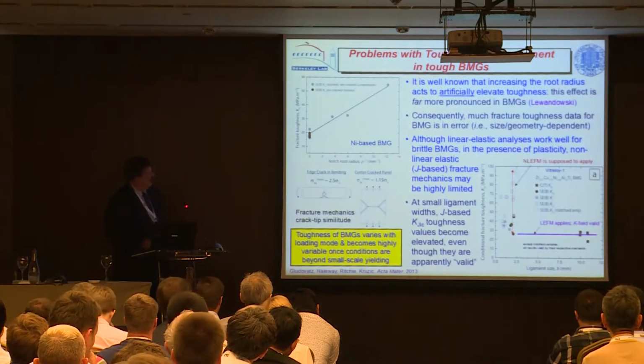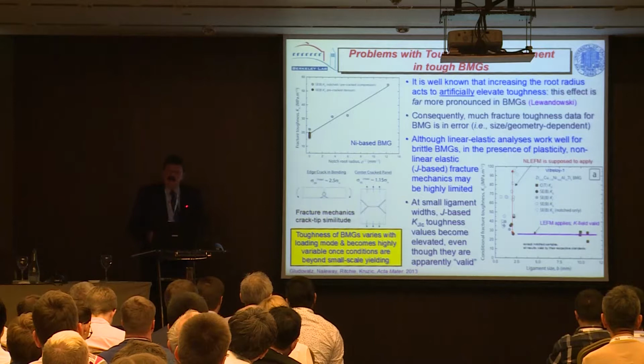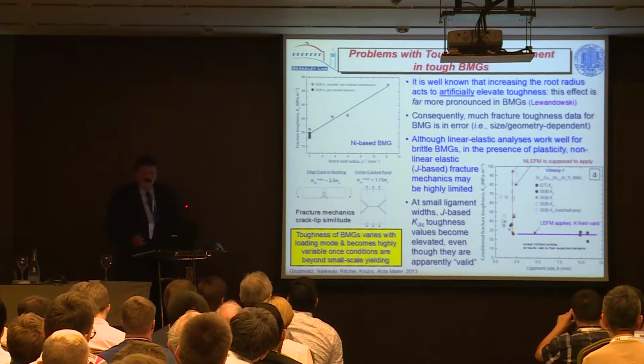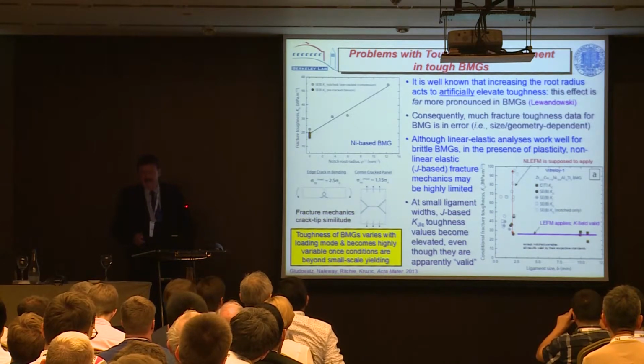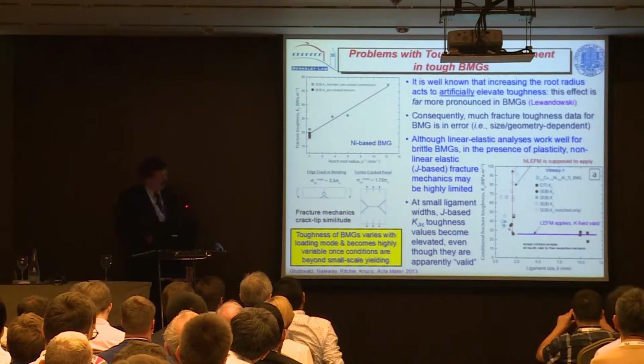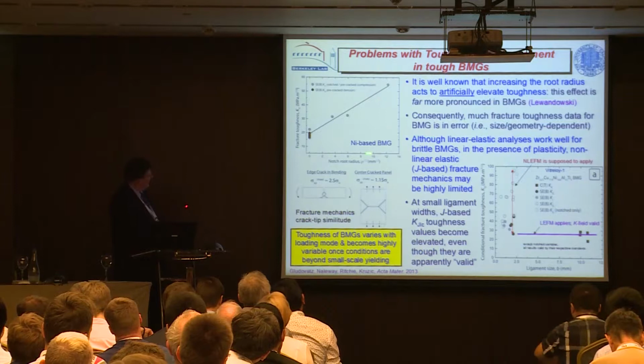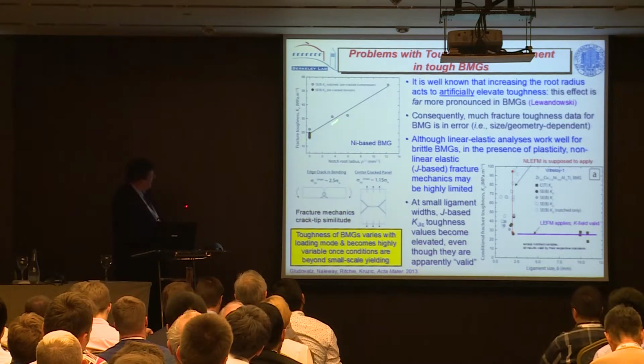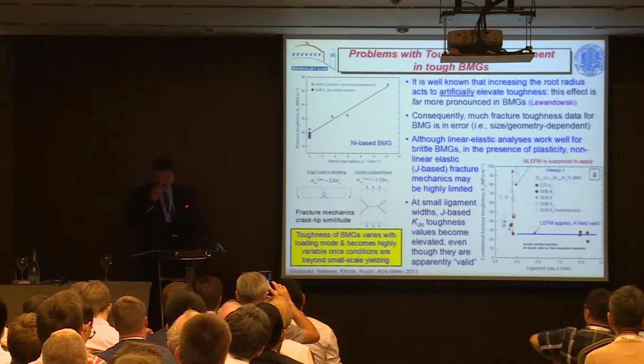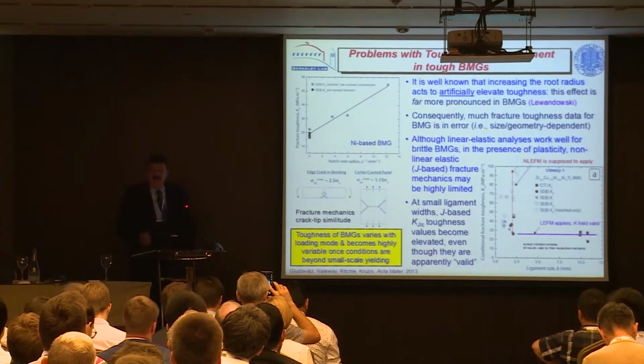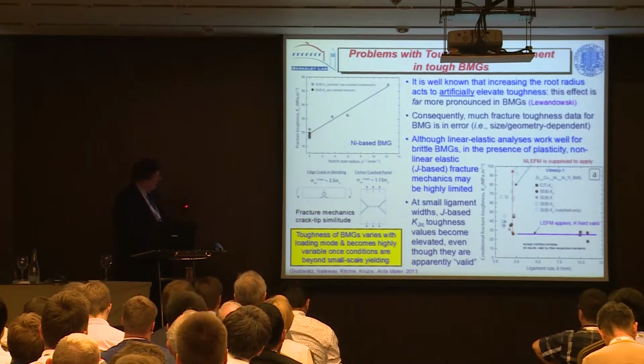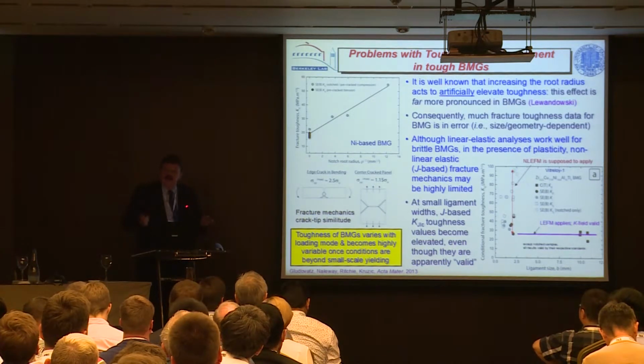So we've been interested in this. There's a lot of variability in the toughness measurements of metallic glasses, mainly because they've been badly measured. There's a lot of people who do notch effects. They measure the notch apparent toughness, and the notch root radius versus the apparent toughness is a very strong effect, much stronger than in regular materials in these glasses. And these are sort of fictitious numbers. So it elevates the toughness erroneously, and people like that.